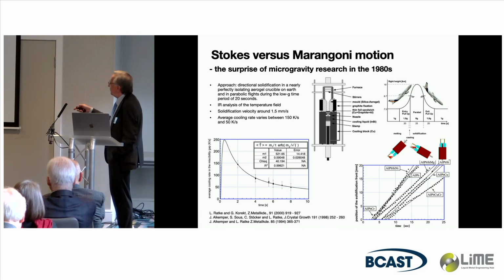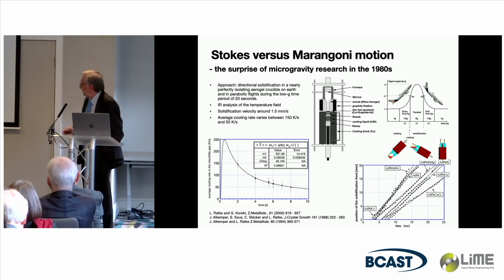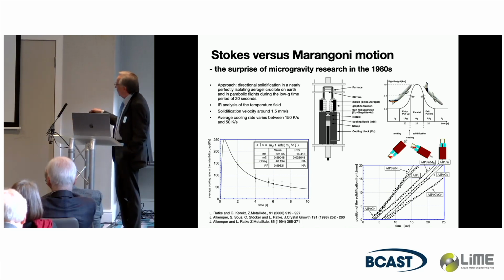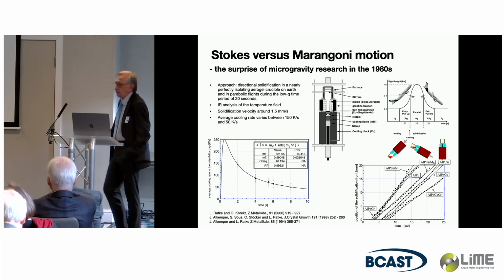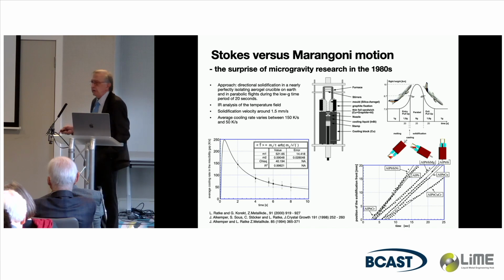So it's almost none of thermal conductivity. So it isolates perfectly. Then it sits in here, and once the microgravity period comes in, you have an indium bismuth alloy and a piston, and bring it here to this small sandwich foil and cool it from the bottom. And if you do everything nicely, you see for all the alloys we investigated, you have something like a solidification velocity of 1.5 millimeter per second. Cooling rate varies, of course.